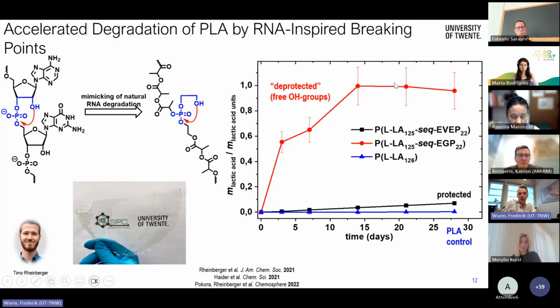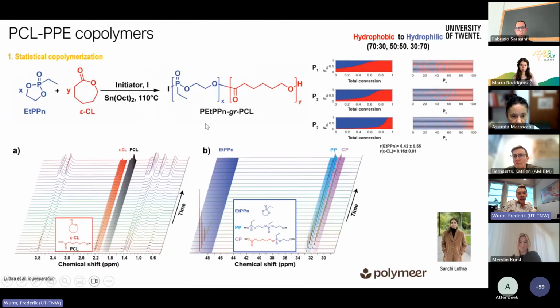this is now artificial seawater. Here we see a much faster hydrolysis in the red curve. So it's just one example, while the normal PLA also, when the OH group here is switched off, we don't see any biodegradation here. And Sanchi and the team was inspired by Timo's work. So she used then first caprolactone, but also can be, of course, obtained from BSG, but is also commercially available. So it's a good starting point here to see how actually such a 7-membered ring can copolymerize with a 5-membered ring. And we want to do this without any solvent.